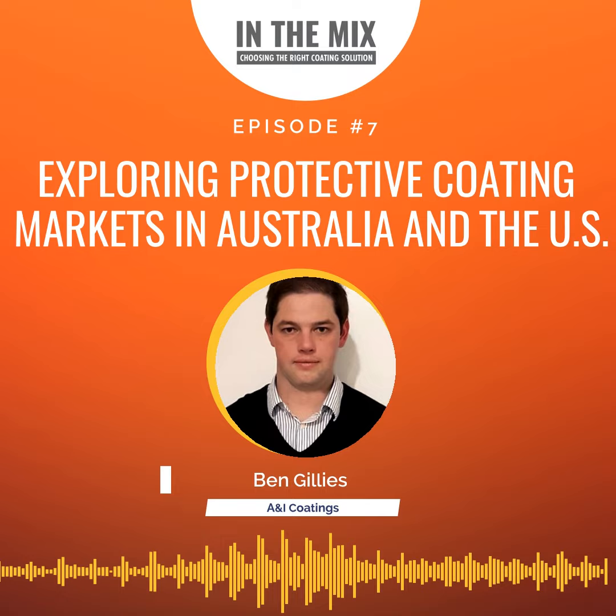But then we might go somewhere really dry like Alice Springs or even Canberra, for example, and we would still recommend using a fluoropolymer, but just without the overall coating thickness. So we might just go 75 microns of zinc-rich epoxy and 75 microns of fluoropolymer. And the reason we would still stick with a fluoropolymer in those less corrosive areas is because it's just going to look better for longer.